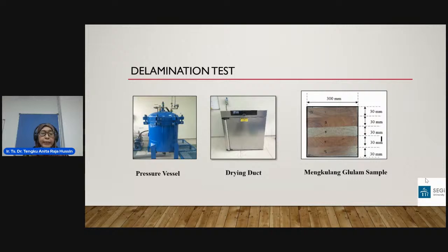This is the delamination test machine that we use. The first one you can see here is the pressure vessel. These apparatus were designed to safely withstand a pressure of at least 87 psi and a vacuum of at least 12 psi.